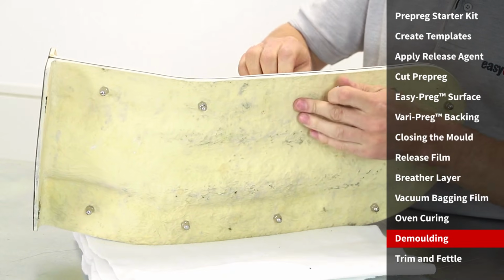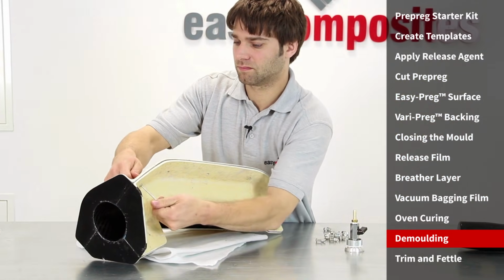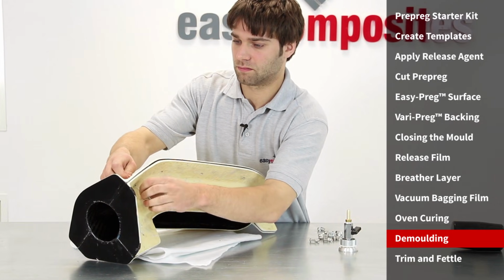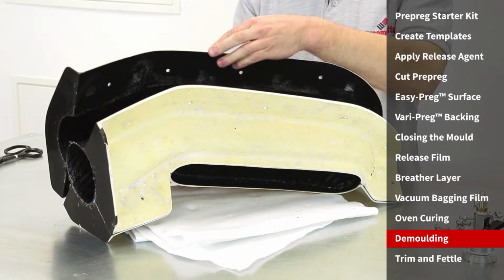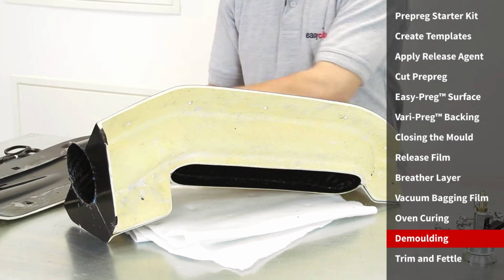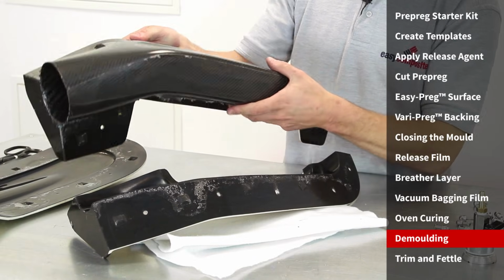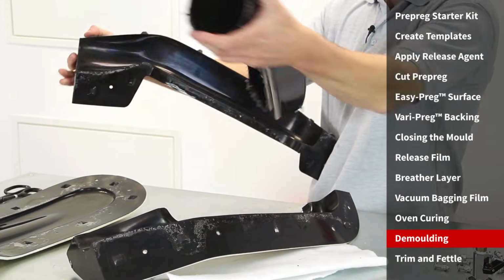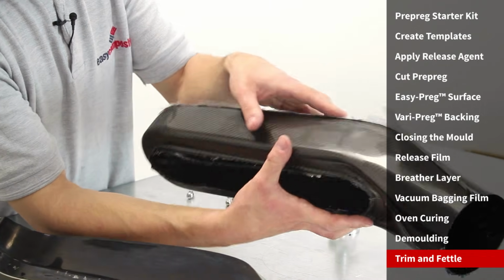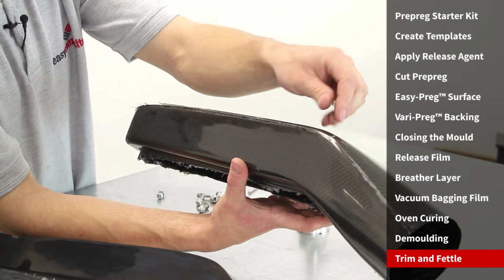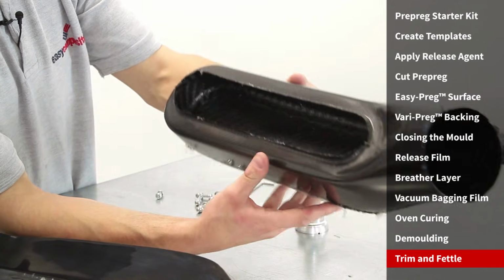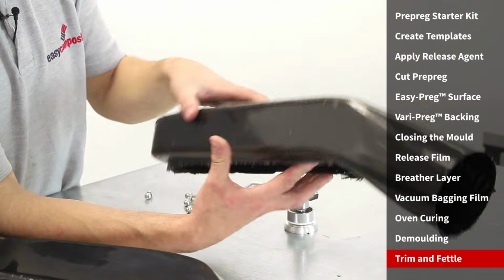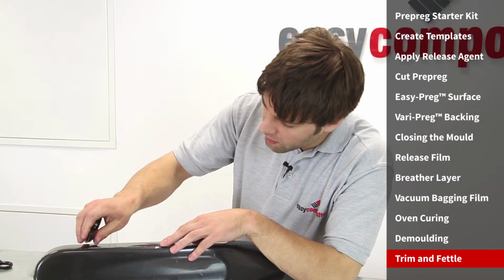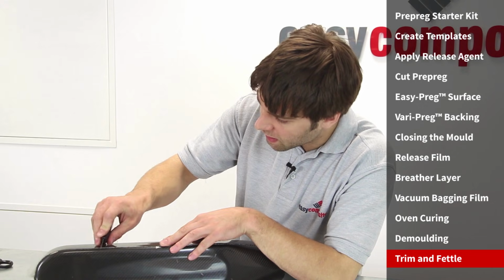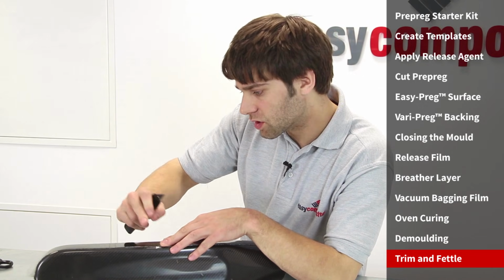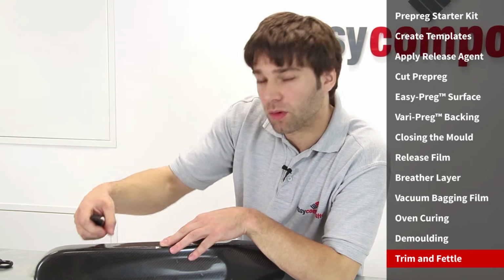Once the consumables have been removed, we can unbolt the various sections of the mould to release the part. The easy release we used earlier ensures that the part releases incredibly easily. So you can see what we're left with here is just some flash lines that can be cleaned up, and then the trim around the lower section to make the final part. A quick way of cleaning up the flash lines is just taking a Stanley blade and scraping it across the surface until the flash has been brought down to a minimum.